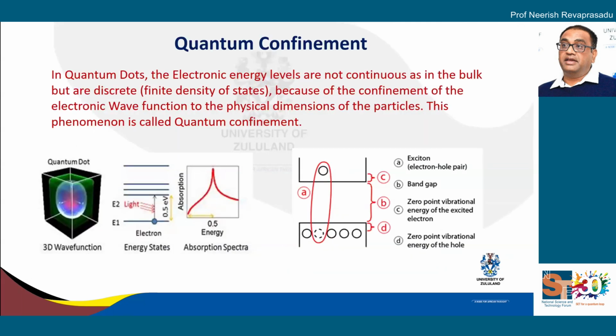Now, I can explain that further. Why do we get an increase in the band gap, and why do we get different colors, which I'll explain in the next slide. So here you see this electron hole can be treated as a particle in a box model. The dimensions of the box are the dimension of the particle, and as you decrease the size of the particle, your energy increases. So you can imagine something being squeezed in the box, and you make the box smaller, and you have an increase in the amplitude of the wave function. So that gives you very simply why the band gap increases.